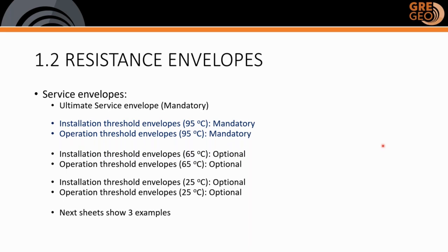The installation threshold and operation threshold envelope described in the guideline are mandatory, and for 65 and 25 C, these are indicated as optional. For the definition of failure, we used damage development that leads to loss of integrity. And the ultimate service envelope shows loads that result in irreversible materials damage, that is typically a catastrophic failure.